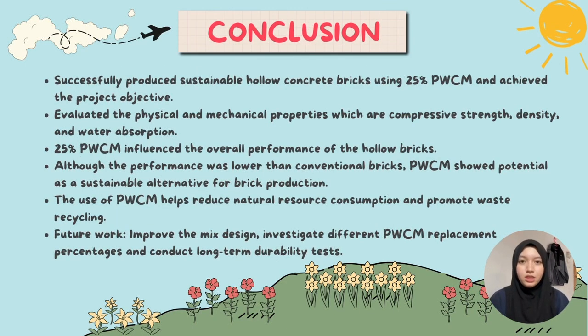In conclusion, this project successfully achieved its objective by producing sustainable hollow concrete brick using a 25% PWCM replacement. The physical and mechanical properties of the brick, including compressive strength, density, and water absorption, were evaluated to assess the performance. The results show that the 25% PWCM replacement influenced the overall performance of the hollow concrete bricks. Although the brick did not perform as well as conventional concrete bricks, the findings demonstrate that PWCM has good potential as a sustainable alternative material for brick production.